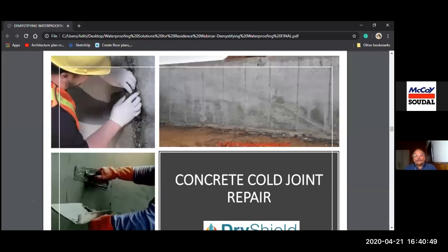I'll never recommend a mortar made at site, which is commonly called polymer modified mortar. If someone wants to use it, fine, but it's always better to use a factory made premix mortar, because the premix repair mortar will have all kind of polymers in it. It will have different types of cements in it. It will have glass fiber or synthetic fibers in it to give it more strength.